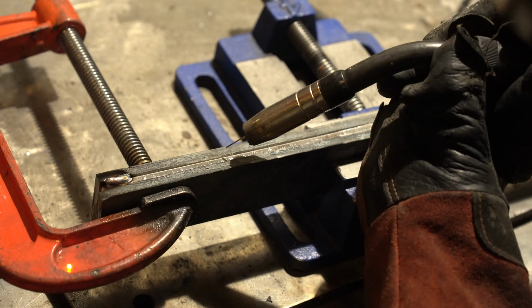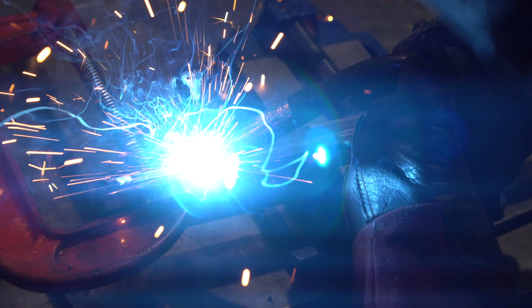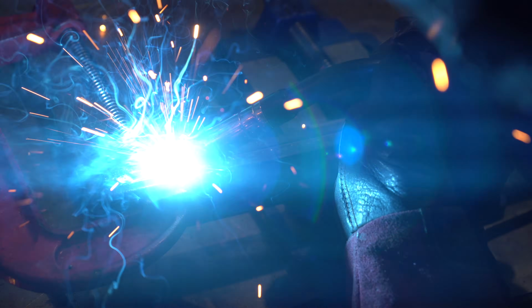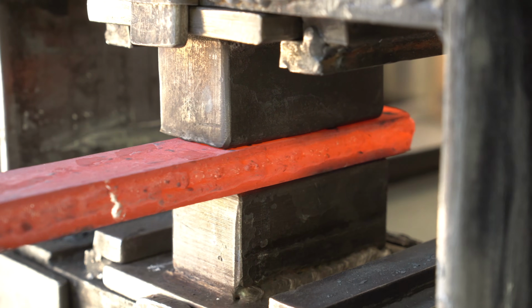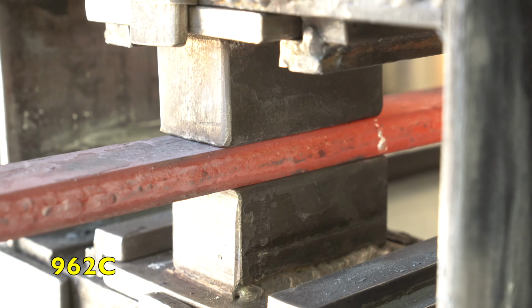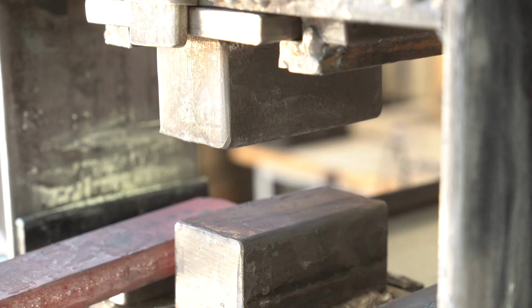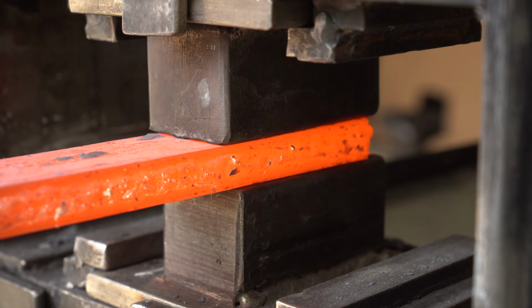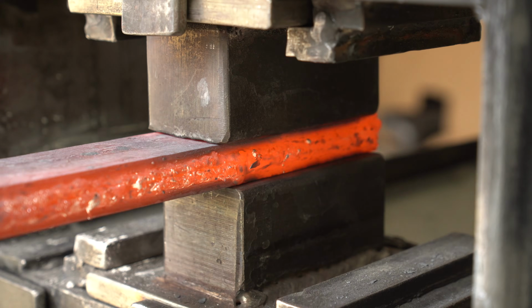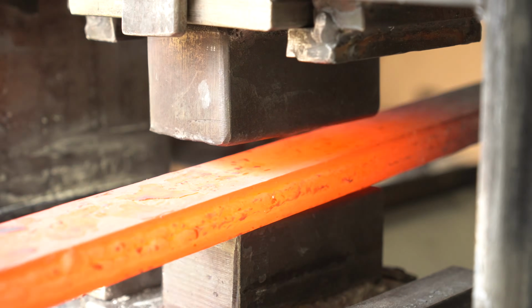It's good practice to weld up all the seams just for insurance, but you really don't want to get the non-ferrous metal melted at any point. Pure silver has a melting point of 1763 degrees Fahrenheit, so we're not technically forge welding this. We're really kind of brazing it all together, so we don't want to get this billet too hot.